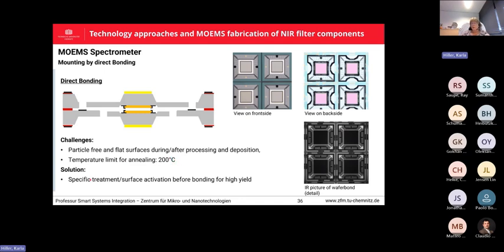So we developed a special process for the surface treatment, including mechanical treatment, like a small polishing step, and also special treatment, including plasma treatment before the bonding. But finally, we managed to have this bonding process very good with a high yield. So this is an infrared transmission picture. This bright frame here is the bonding frame. The dark areas are not transparent in this light, and so we can also control the yield of our bonding process.